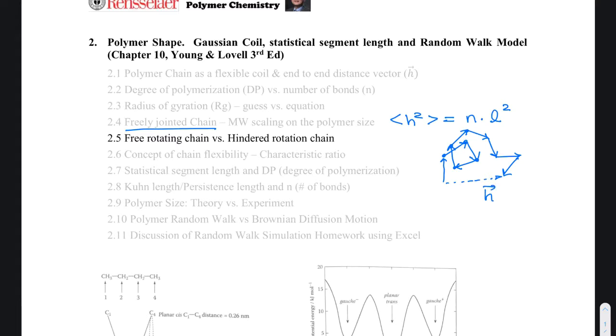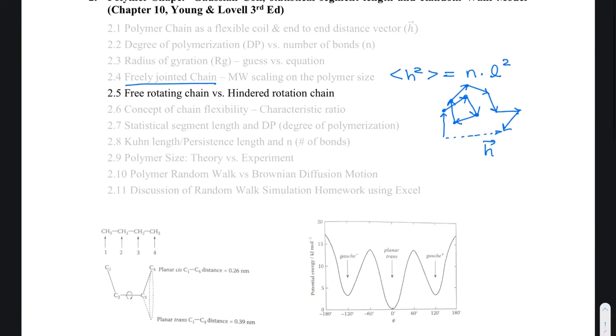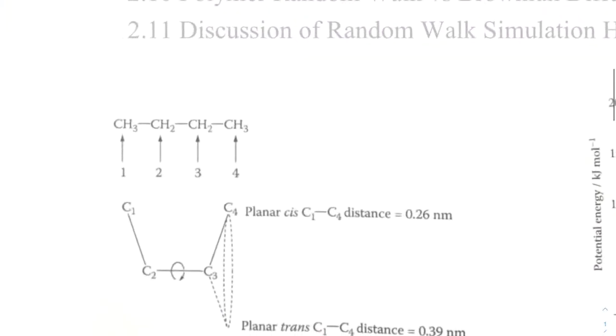But let's start. I'll go back to our days in the organic chemistry. So remember, when you learn about the chain conformation, and I think that you learn about the Newman projections, and we are considering this four carbon, which is the butane case. And then you have first carbon, second carbon, third carbon. And this is a case when you are in the cis position, and cis, what we call the eclipse position, and then the distance between this is 0.26 nanometers.